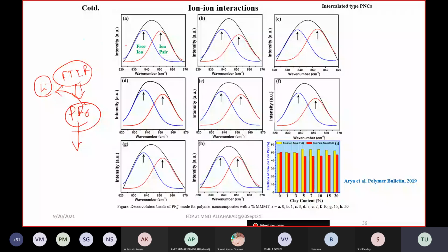So on that basis, the PF6 band is characterized here, and it is seen when it is a polymer salt complex, then the contribution of ion pair and free ion. Whatever the higher wave number is, it is associated with the ion pair formation, and which one is lower. Since nu is equal to 1 over 2 pi under root k upon mu, this k, the force constant, is large in ion pair formation, so its wave number is going to be large. Whereas in this one, it is to be a lower value.